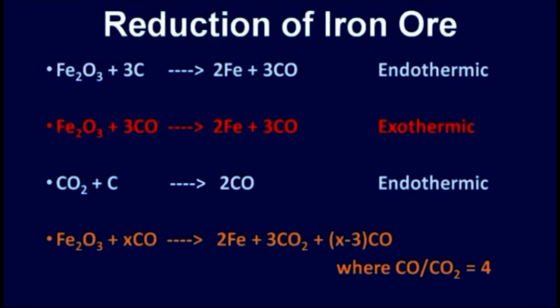Another reaction which is very important is the Boudouard reaction, CO2 plus C equals 2CO. It has also been found that when the carbon monoxide to carbon dioxide ratio is 4, the furnace operation is best. Carbon monoxide is more stable at high temperature.